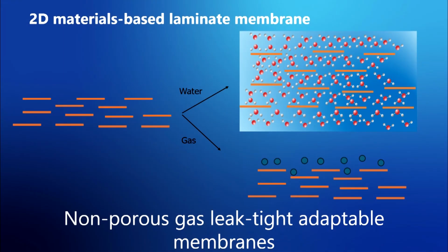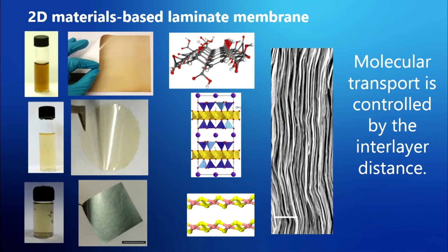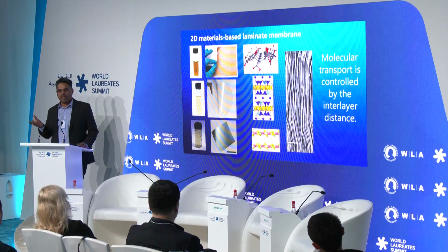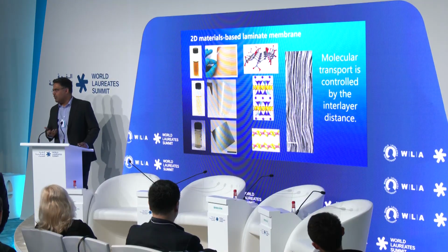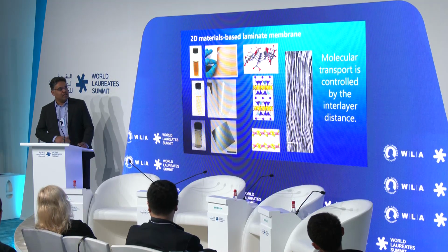So we have been working on such membranes for more than a decade now, from small scale to large scale. And membranes are not just limited to graphene oxide. We can develop such membranes based on different materials like graphene, graphene oxide, clays, for example vermiculite, molybdenum disulfide, and even now MXene, and so on. All of these materials are processable in liquids, like you can make graphene oxide in water, MXene in water, MoS2 in water, and so on. And then you create a membrane.